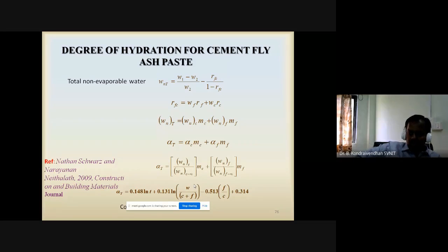We did a lot of experimental work, and we determined the degree of hydration for various water cement ratios and curing ages, and finally we did least square based regression analysis. Finally, we got the total degree of hydration for the cement fly ash paste as a function of curing age and water cement ratio, otherwise I can say W by C plus F, and also F by C ratio. So if you know these three parameters, you can determine the degree of hydration for the cement fly ash system. So we determined the degree of hydration as a function of water binder ratio, F by C ratio, and age.